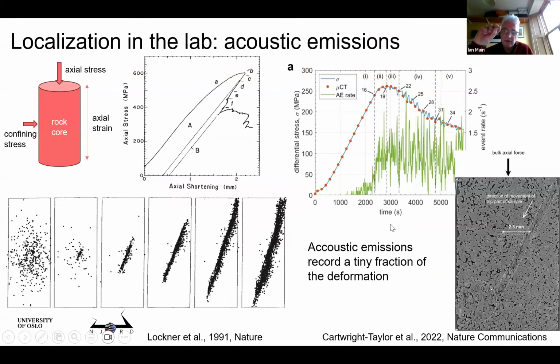And then it begins to nucleate a zone of high strain, which then grows, as in his experimental results with the acoustic emissions. So that thing there on the left, when we did this, there was already a shear band going across the sample. And then you got the localization of strain on a small patch, which kind of grows through the test. So these long range correlations are there. It decides that pretty early, in between two snapshots, and then the strain localizes and grows along. So I don't know how it does it really, but it's finding this optimum angle pretty early.